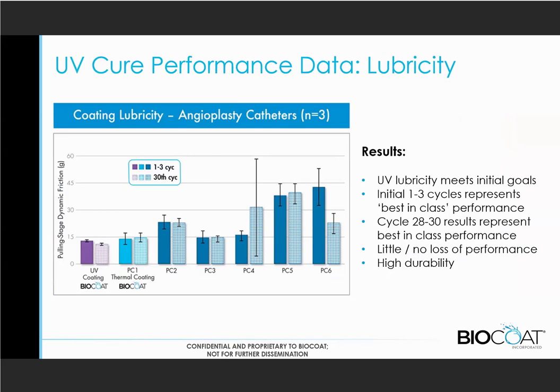There are some that have good initial lubricity and also good durability. There are other ones, such as the PC4, that do not have as good durability, where some of the coating is wearing off and there's higher variation over time. In contrast and comparison, the UV coating has very similar performance to our thermal coating. That was done on catheter tubing that we weighed into here. So we had good lubricity, with very little loss of performance and durability.